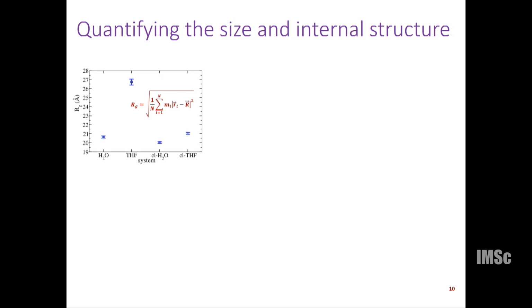So you can see in THF consistently the structure has higher size as compared to that in water. Okay, so this is with cross-links and this is without cross-links. So what we do see is that when we have cross-linking, the increase in the size is not as much as the other case. So in other words, we can say that the structure is retaining its internal architecture and swelling.